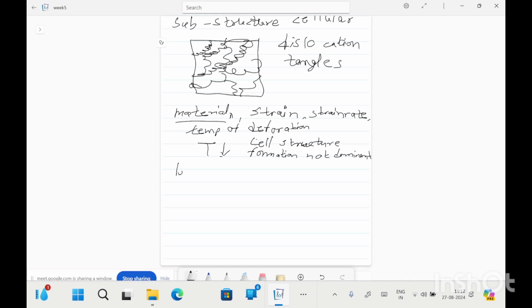And it is also true for low stacking fault energy material. Means if stacking fault energy is low, then the dislocation movement will be hampered and the formation of cellular substructure will be less favored. With low stacking fault energy, low cross slip will happen. So if the dislocation cannot cross slip, deformation will be restricted and the substructure will not form. One more thing, at high strain rate, this phenomenon is also less pronounced, means the structure will not form.